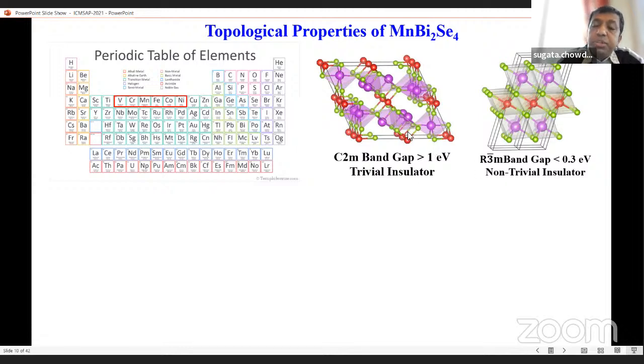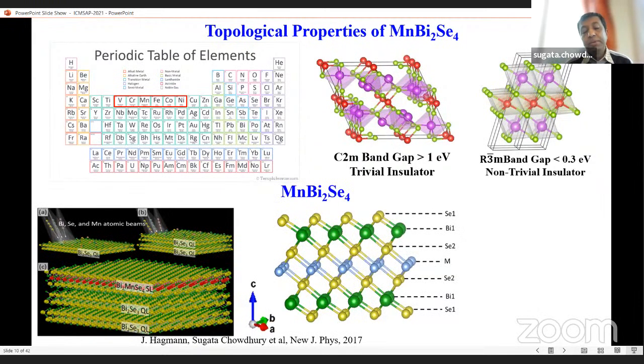The most important thing is that naturally the manganese bismuth selenide has the C2/m symmetry as its ground state, and synthesizing a single crystal always moves in that direction. To create R3m, which shows a different kind of topological property, you need thin film synthesis or MBE growth. At NIST, my collaborator Joe Hagmann developed a method, and they synthesized bismuth selenide quintuple layer and bismuth manganese selenide septuple layer. That was the first development of any kind of manganese bismuth selenide structure synthesis process.